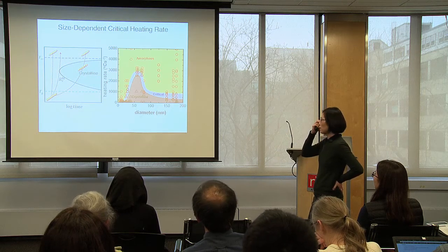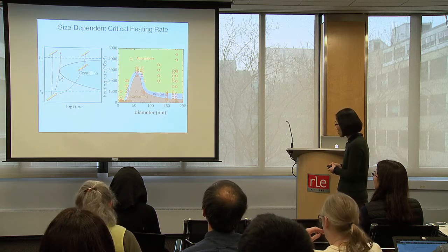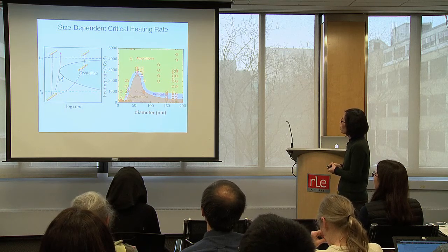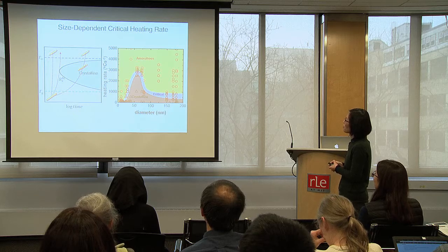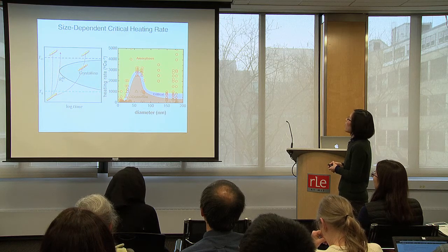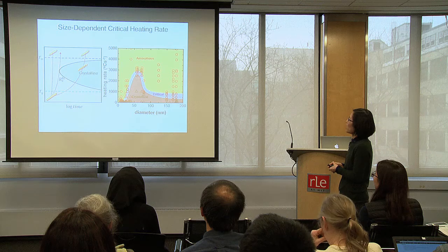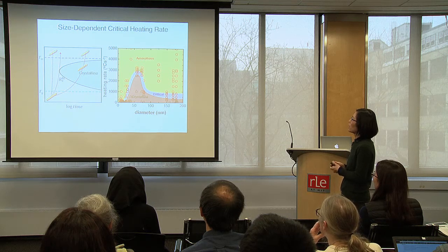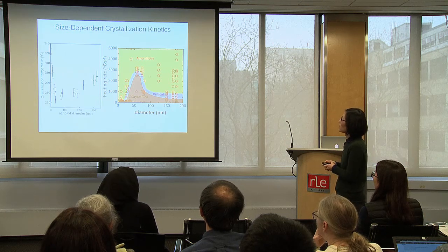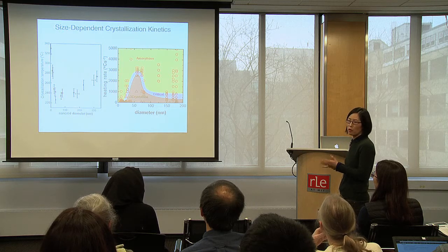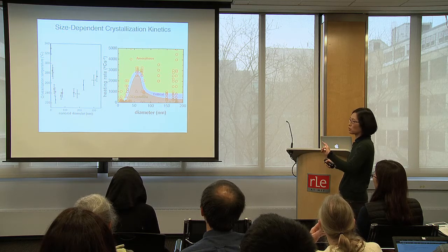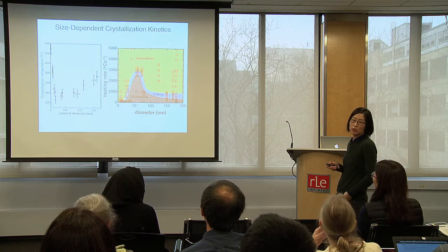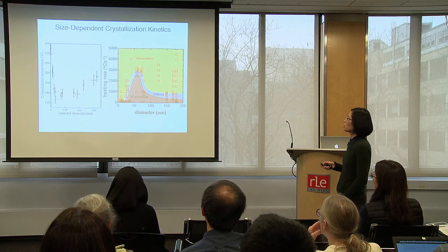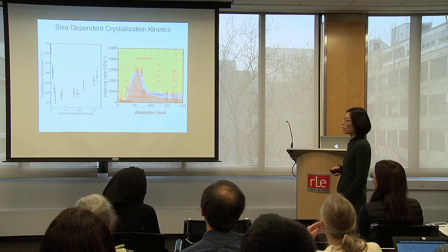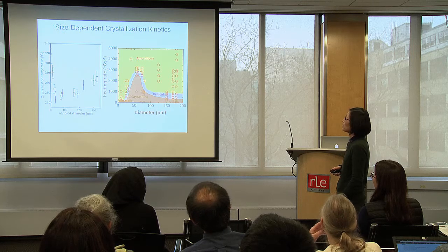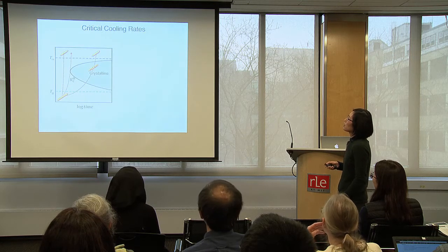So here's the summary of the data. So as a function of the nanorod diameter, we are repeating experiments at many different rates. Okay? And right here is the critical rate. Okay? So one sanity check is that this result agrees with our previous result because this is a rate, so it's sort of inverse of the crystallization temperature. So this non-monotonic shape, we preserve that. So that's good. This was critical heating.